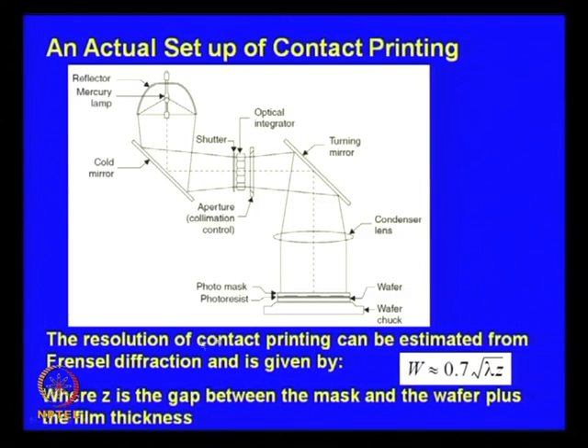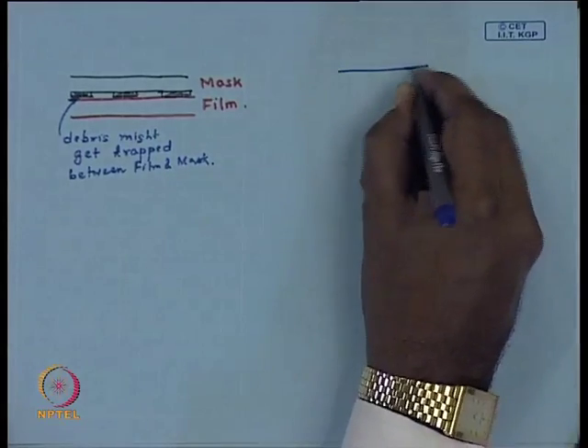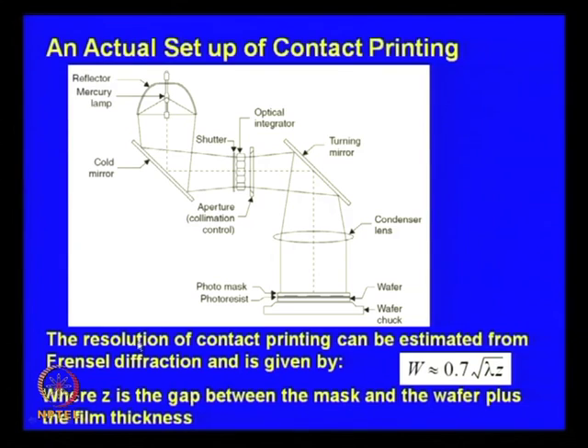The resolution of the contact printing can be estimated from the Fresnel diffraction, and which can be given as 0.7 times under root lambda into z, where z is the gap between the mask and the wafer plus the film thickness. We will probably realize what is the gap between the mask and the wafer in the subsequent slide. So, this is simple to calculate, because this positioning etcetera is not manual. So, you have an automatic positioner. So, you can calculate z and you can estimate what sort of resolution you are likely to get.